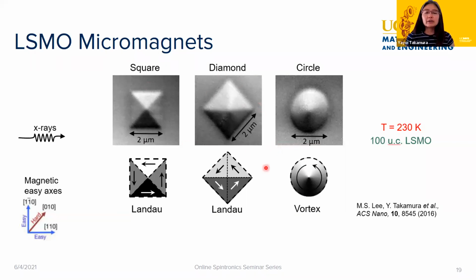And so again, what I have here is, we've patterned these LSMO with our ion implanted technique. So this gray region outside of all of our shapes is that implanted matrix, so it's non-magnetic. And we pattern them in fairly large structures at 2 microns, either in diameter or in terms of the length. I always feel that people always want to go smaller, nano, but we actually find that this micron scale is where we get some really interesting physics, and so we've focused quite a bit of our effort on looking at these dimensions.